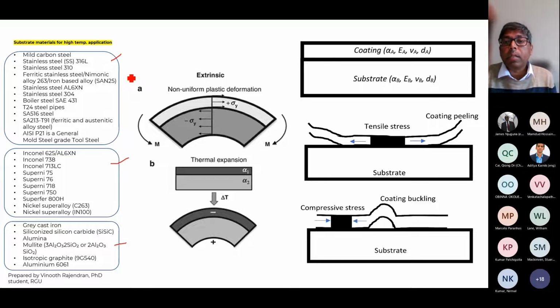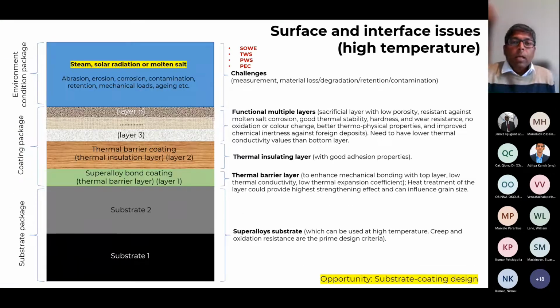This is just a simple example of a single layer, because you have a different substrate, different elastic modulus, different Poisson ratio, different thickness. So whatever you do on top of that is likely to change as soon as you do the coating, and also when applied in various temperature conditions. Now, surface and interface is an issue, in how you manufacture it.